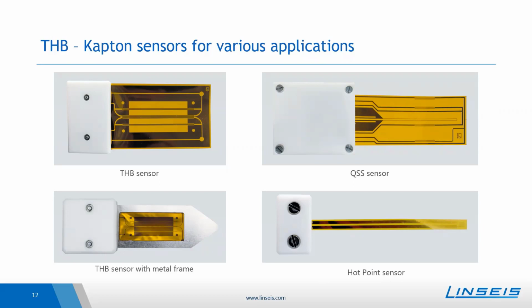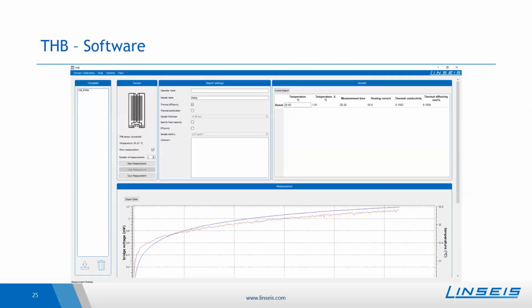Within the software, one can also have a look at the penetration depth. So in the software, you can also select here thermal penetration. Then it will also calculate an estimation on how deep the heat generated by the sensor penetrated into the material. For lower conductive materials, this is typically between 2 to 3 millimeters, and the higher conductive the material, the higher will be also the penetration depth. But mostly it stays within a few millimeters.